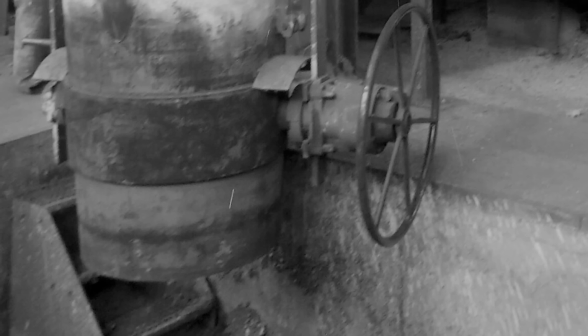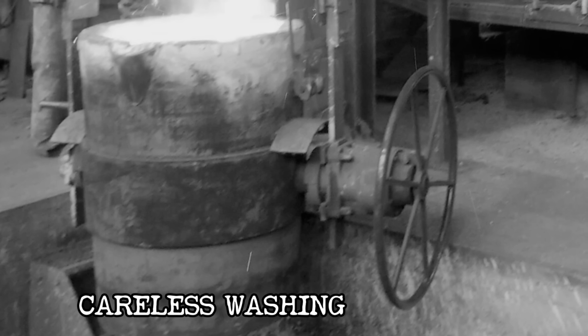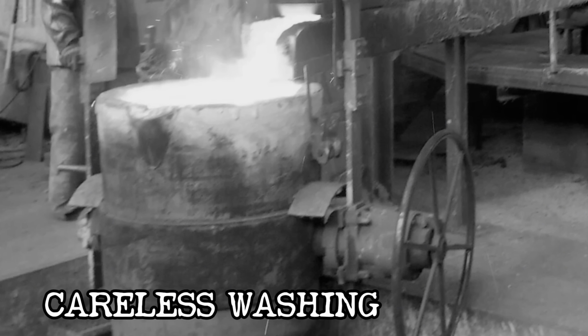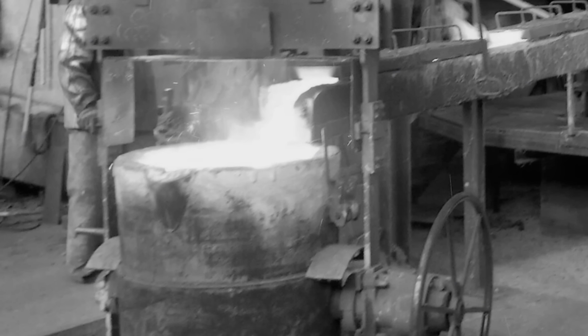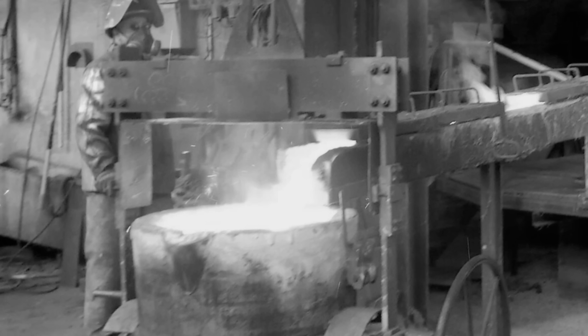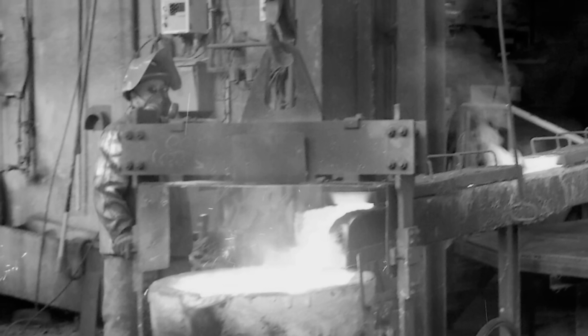The span breaks, the ladle tilts. 9,000 pounds of molten steel, already pouring from the tap hole, sloshes violently to one side. Some of it stays in the ladle, most of it doesn't. It spills onto the foundry floor, onto the wet sand used for mold making, onto the damp concrete, onto puddles of water that condensation and careless washing had left behind. And then the floor explodes. Not figuratively, literally. When molten steel at 2,800 degrees Fahrenheit hits water, the water doesn't have time to boil normally. It flash converts to steam.